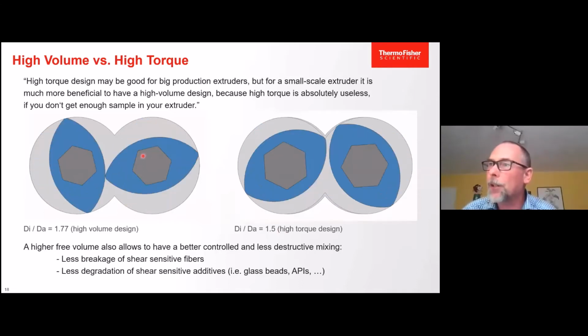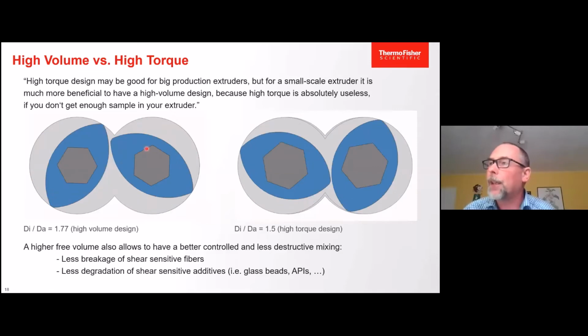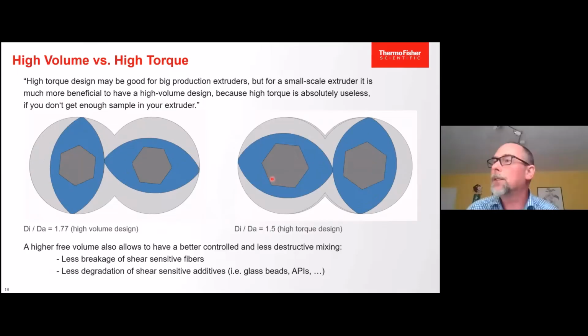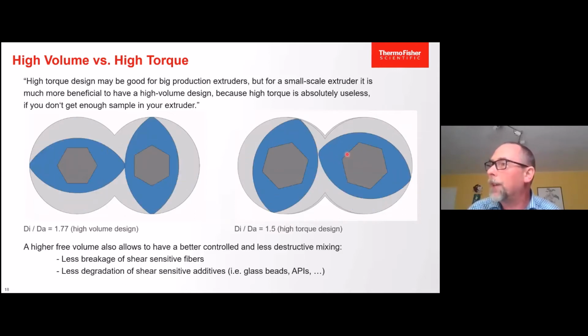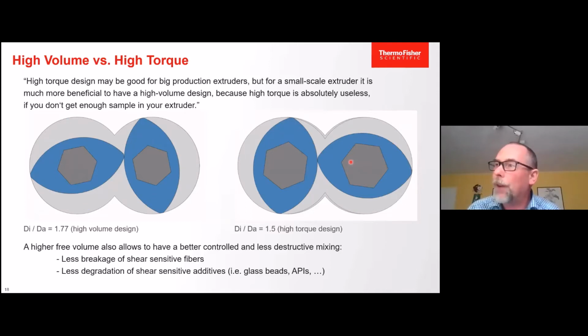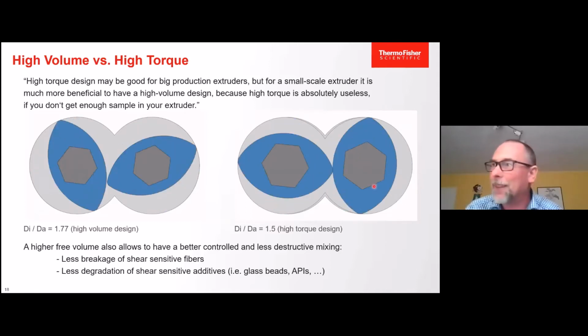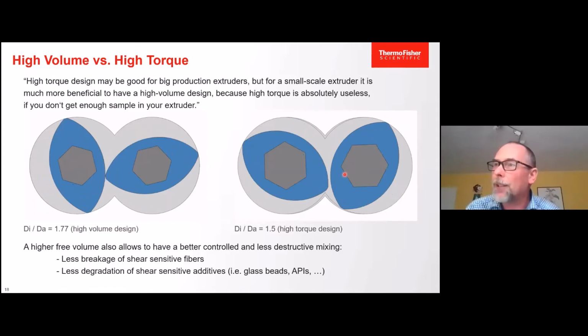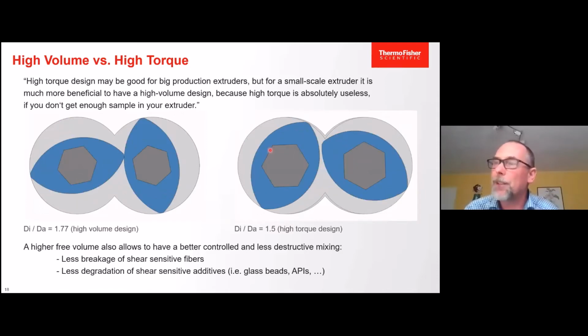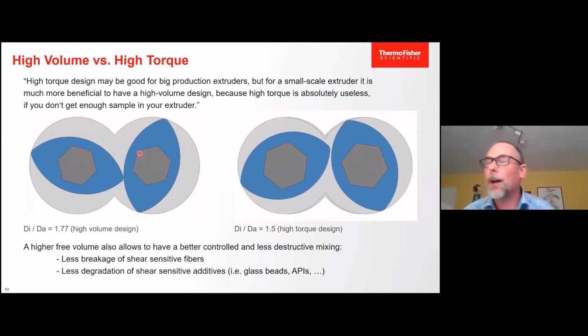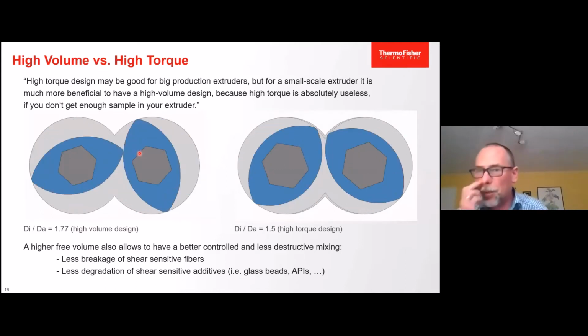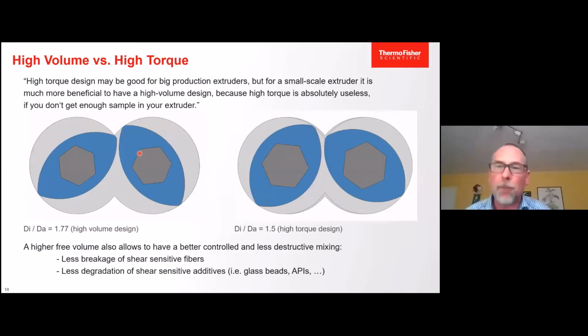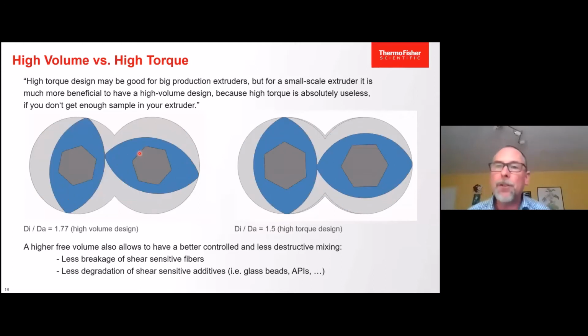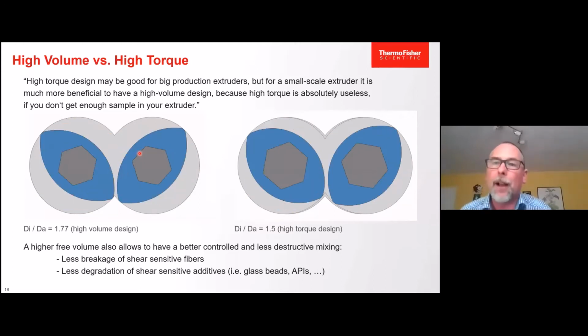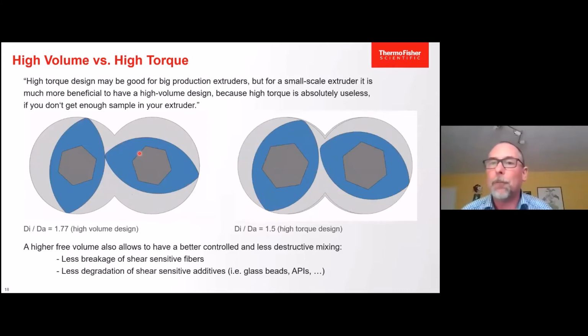You see the hexagonal screw shaft over here. If we would make a small volume design, a high torque design, we would have here a very big piece of metal actually. And so this gives us a higher torque compared to a smaller screw shaft. So we always have to find a balance, high torque, high volume. High torque for industry is good if it comes to maximum output to run a process 24 hours, that is clear. But usually those extruders are much bigger and will not look at feeding problems.